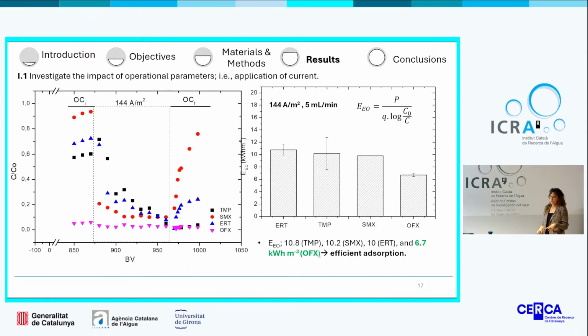To investigate the impact of the current on all the studied antibiotics, we ran the treatment for 48 hours in order to get partial saturation of the sponge, and after this we applied the highest current into the reactor. According to this graph, we could observe a gradual decrease of the concentrations in the case of all the studied antibiotics, till almost complete removal.